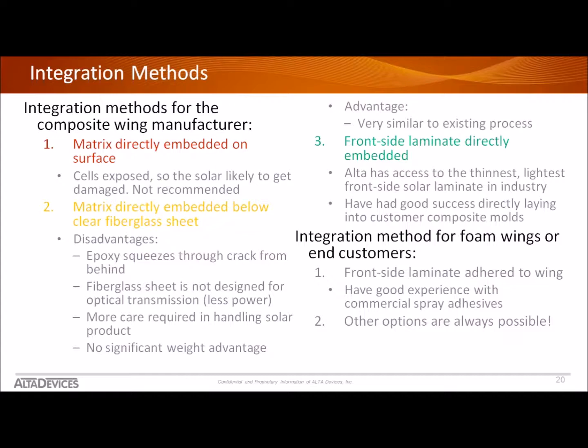Another thing we have tried is to directly embed below a clear fiberglass sheet if you've got fiberglass composite wings. The disadvantages we found is that often the epoxy that you put behind the solar cell can squeeze between the cracks, shading part of the solar material. And also that fiberglass sheet you're using to protect the solar material is not designed to be optically transmissive, and so you're going to lose more power than if you used a solar front sheet. And then because you're handling bare matrices when integrating, you have to take more care, and damage is possible. And the other thing is you're not really getting a weight advantage by using the fiberglass material, because a lot of our solar materials are just as lightweight or almost as lightweight.